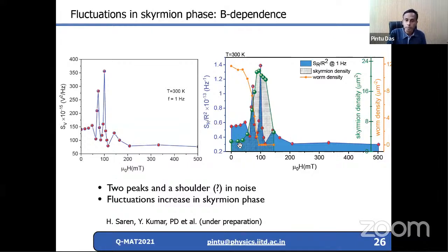On the right side, I plot the noise along with the skyrmion and worm density, and you see that these two peaks are coming in the region of the skyrmions. Interestingly, the first peak is appearing when the worm density has a very strong slope. So that means here it's in the mixed phase, both worm and skyrmion.